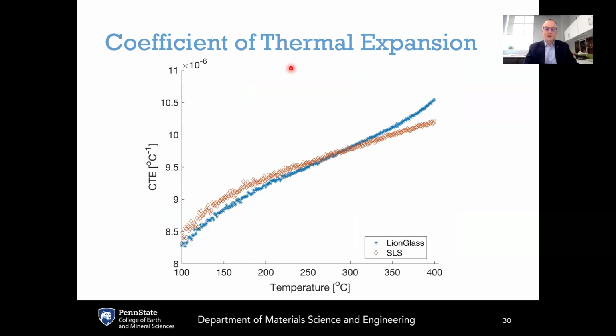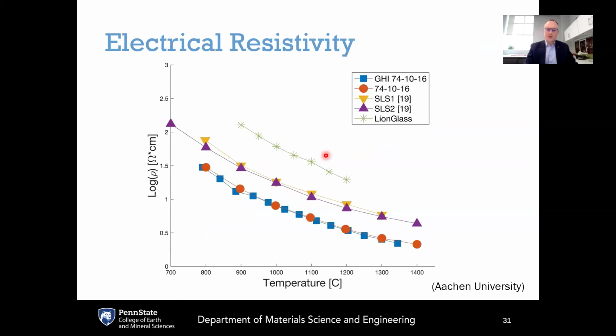When it comes to coefficient of thermal expansion, it is centered around the same CTE as soda lime silicate. You can see soda lime here in the brownish color and LionGlass in blue, and they are very similar. Depending upon where you are in the compositional range of LionGlass, you can shift this either up or down. But overall, the CTE is pretty similar to what we get with soda lime, which means that you can also use this for thermal tempering, although the temperatures that are used for tempering would, of course, be lower.